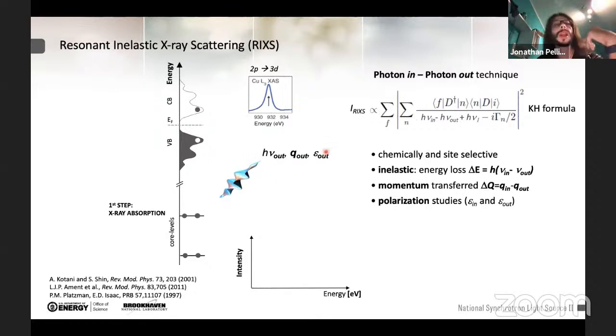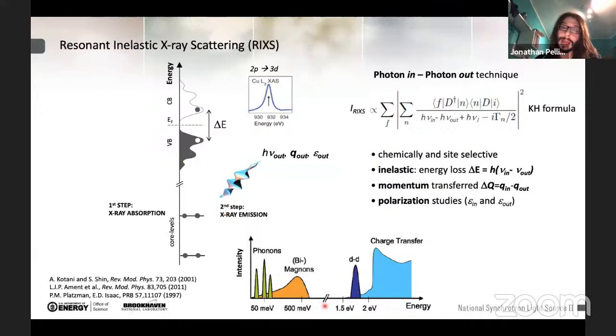And if we look at how we left the system, it is left with a hole in the valence band and an electron in the conduction band, which means that it has acquired an energy. And when we analyze the incident and outgoing photon, we can essentially detect a peak as a function of energy loss, which corresponds to this excitation. This is extremely important because, depending on this energy analysis, we can uncover, as I said before, charge transfer, dd excitation, magnon excitation, and phonons.